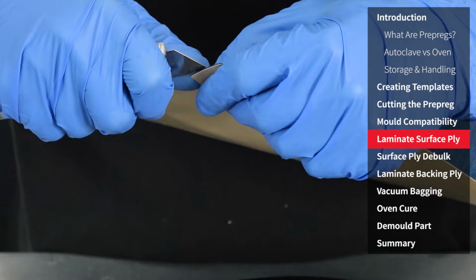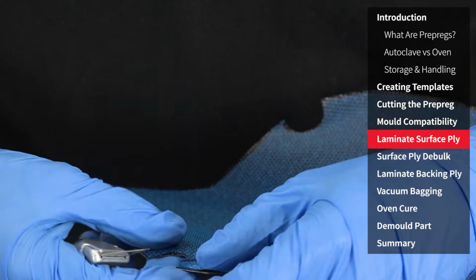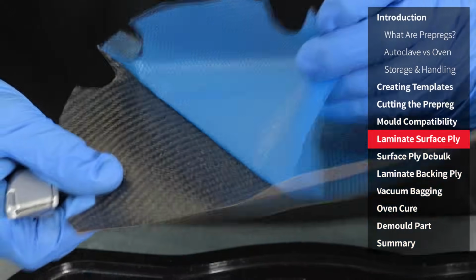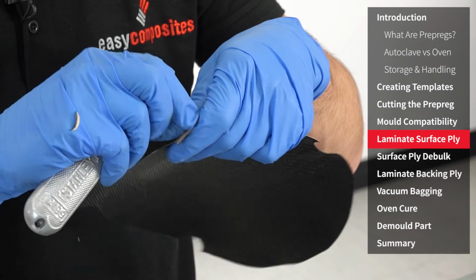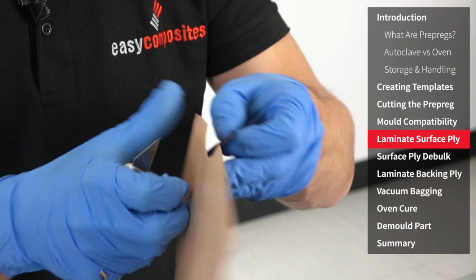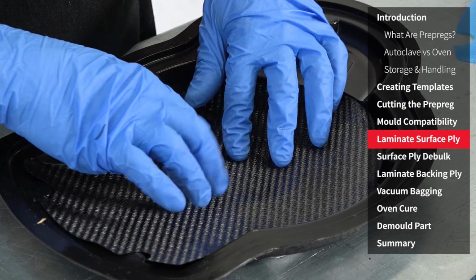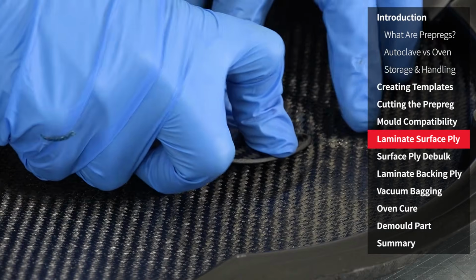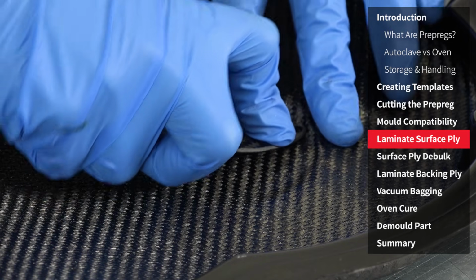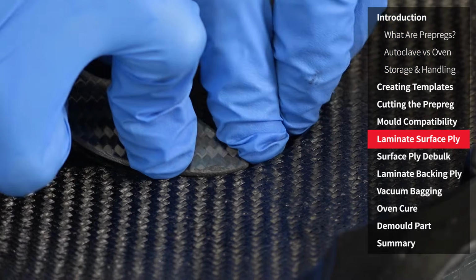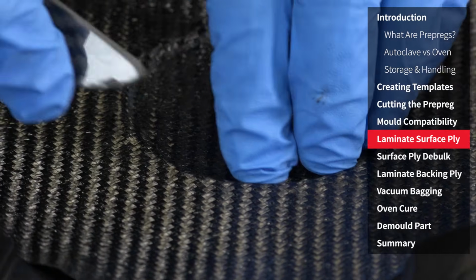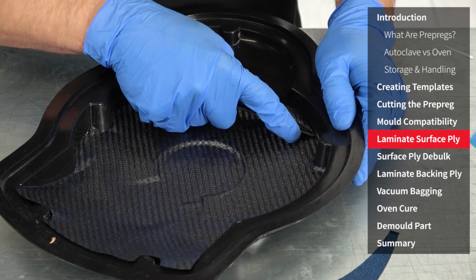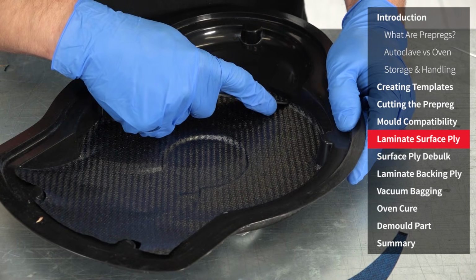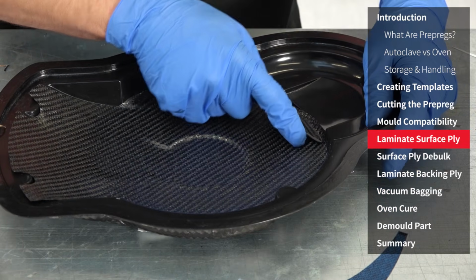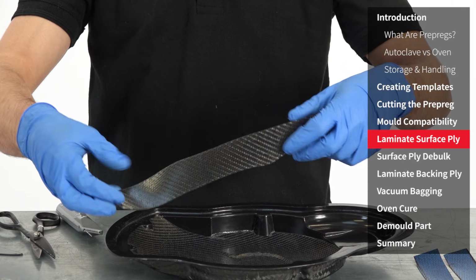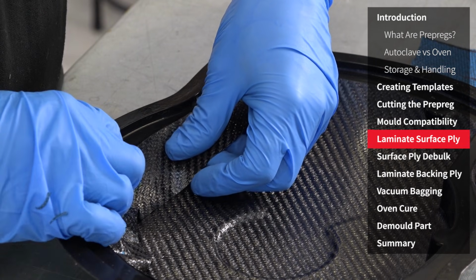Laminating with pre-preg is actually very easy. In fact, the hardest part is probably removing the backing plastic. A thorough and methodical approach is required to ensure that the material is laminated correctly. The aim is to ensure that the material is in intimate contact with the entire mould surface. To achieve this, you should systematically work the material down, starting from a centre point and working outward. Depending on the job in hand, there are a number of different laminating tools that can be used, ranging from rollers to the back of shears. On this job, I'm using a tool that I shaped from a piece of carbon fibre sheet.